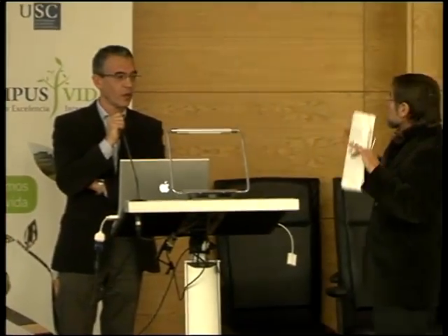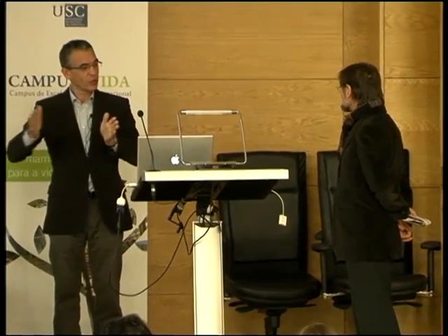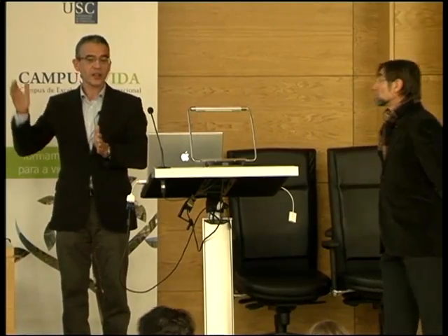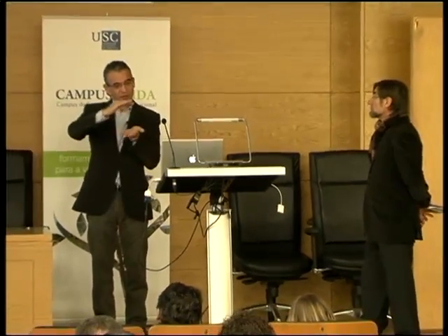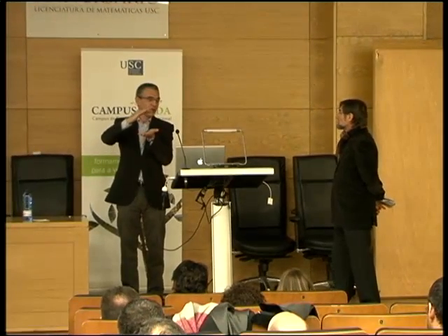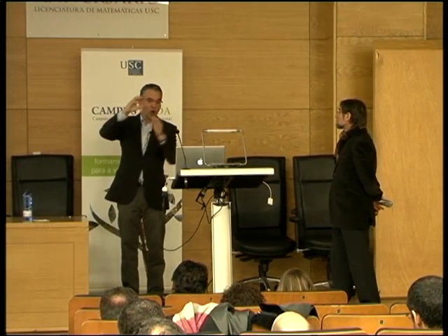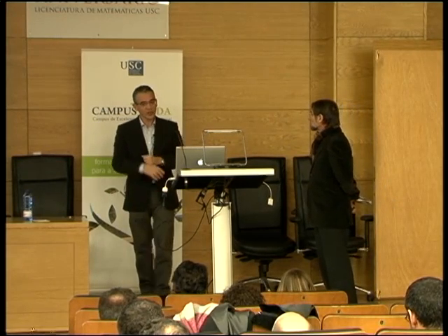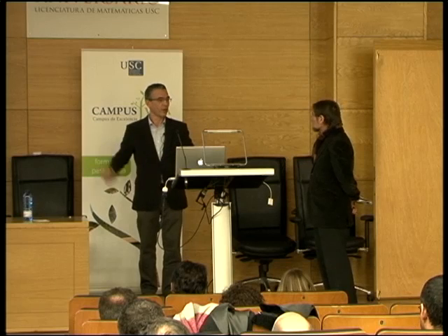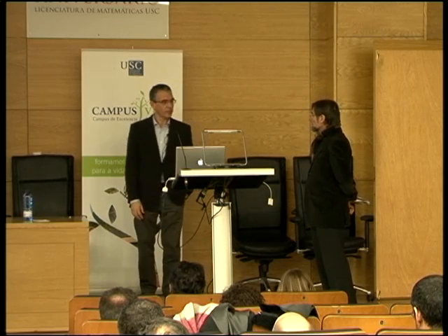Just a curiosity, when you made the nanotubes, what is the length of the nanotube? That's one of the limitations of that kind of model: once they start to assemble, it's very difficult to stop. Only in the case of the peptide that goes to the membrane do you control the length, because only the hydrophobic part will facilitate the formation of the tube. If it's in aqueous media, they will grow to a few micrometers in length.